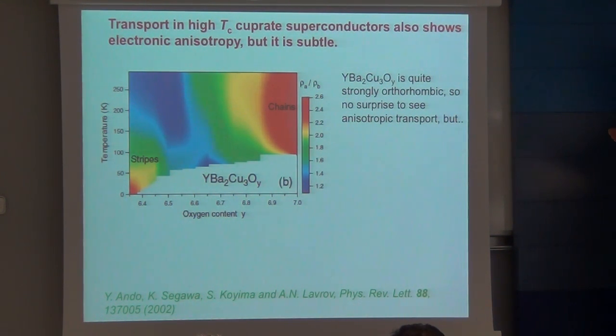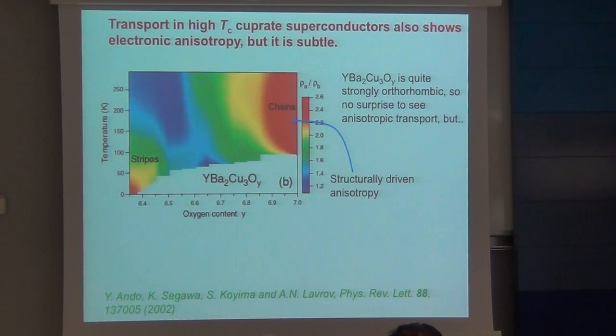It's twofold symmetric already, right? And therefore, people had done a lot of work looking up here at where they found that red here means there's a strong transport anisotropy. That wasn't a surprise to anybody, because everybody expected that in a very anisotropic structure you would see an anisotropic response.